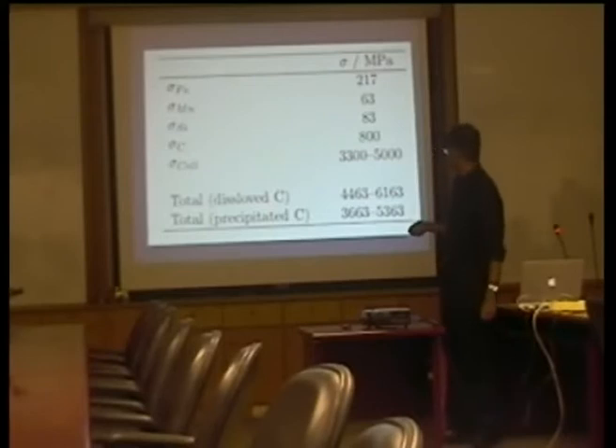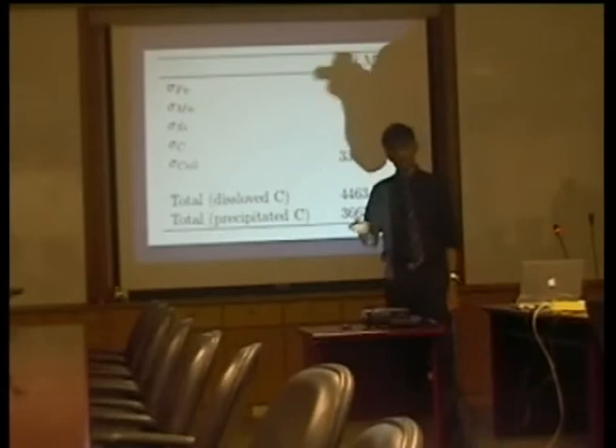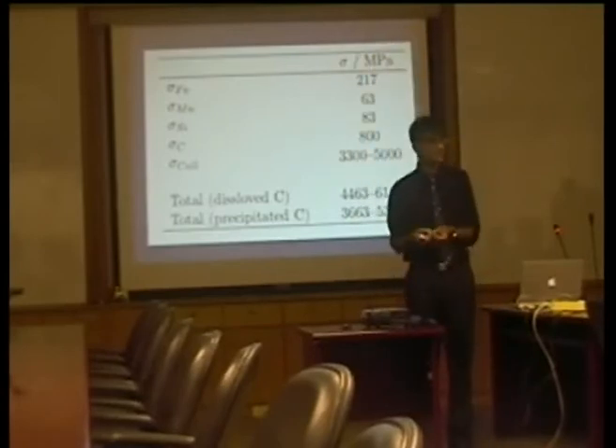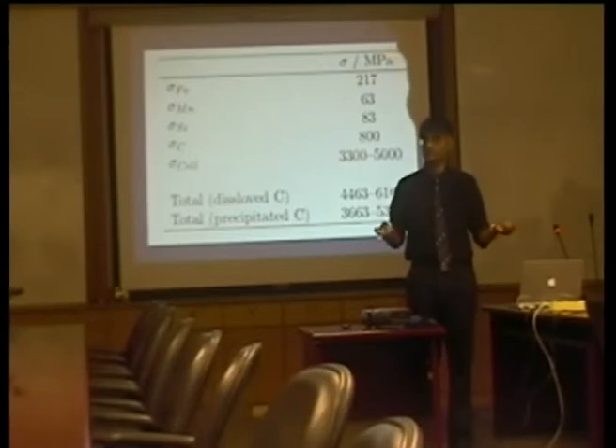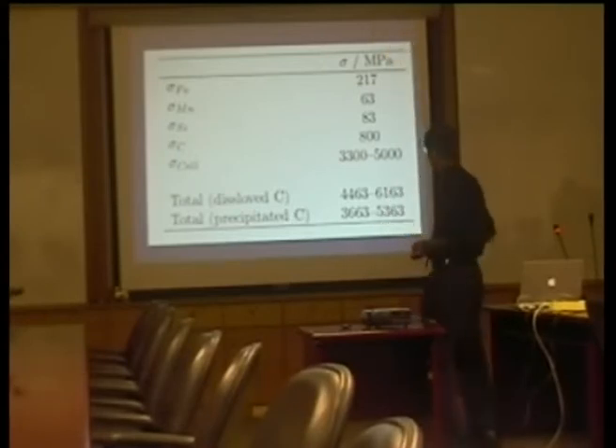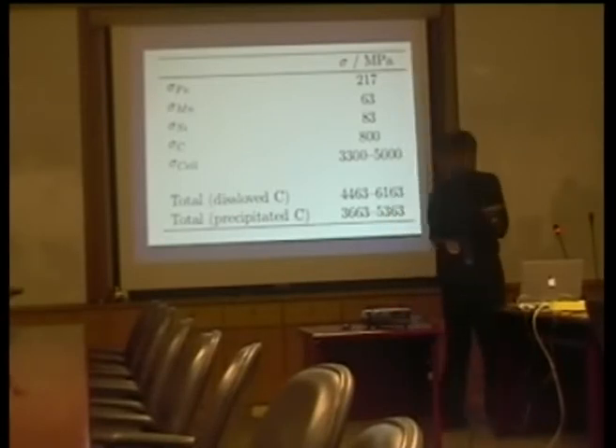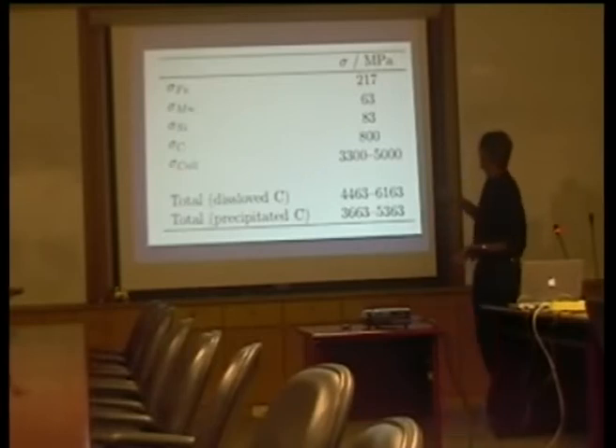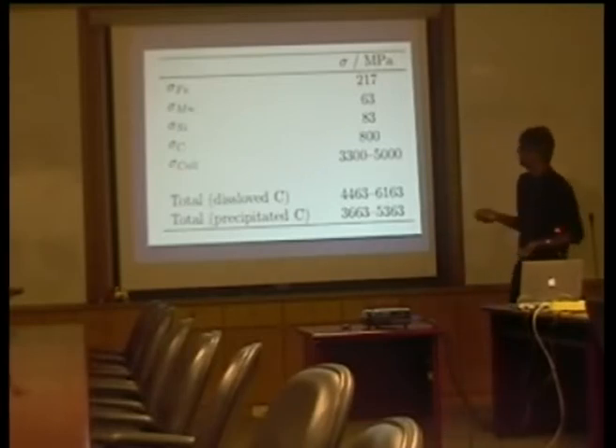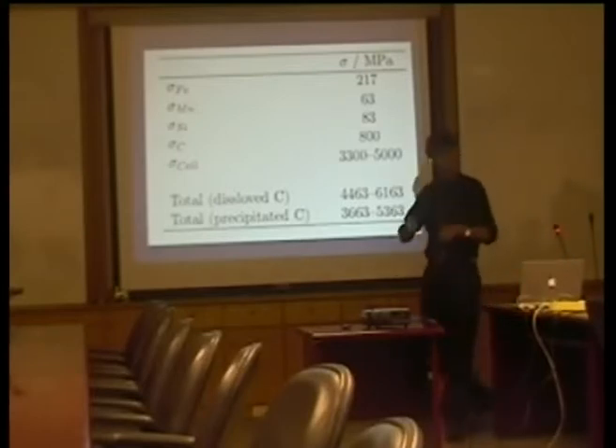So you can see here that I expect to see something from 3.3 to 5 gigapascals of strength coming just from the fine grain size due to the severe deformation. Now, of course, there is a strength coming from the iron itself. Even if it didn't have any microstructure, it would have a strength of about that much. The solid solution strengthening is a very small contribution. Carbon would contribute something like 800 megapascals if it was completely in solid solution.